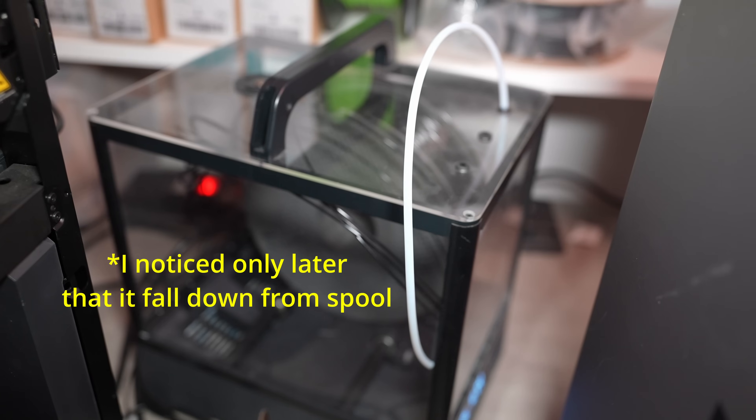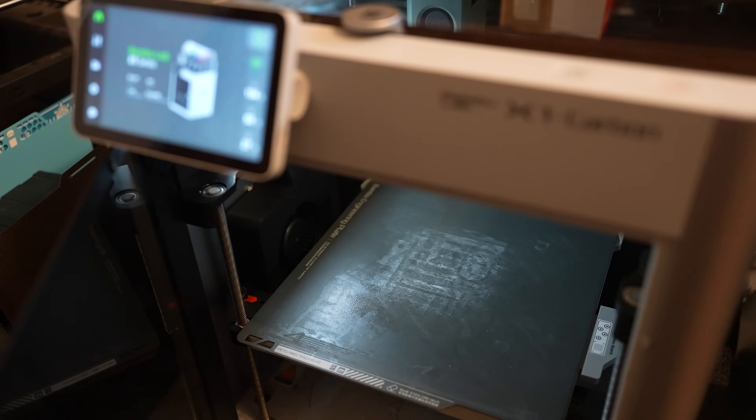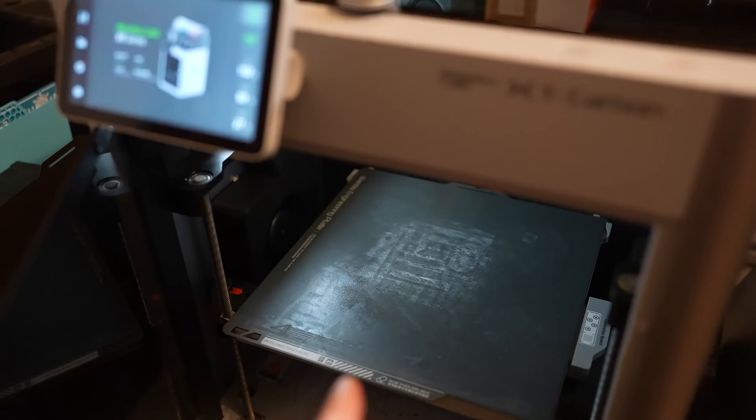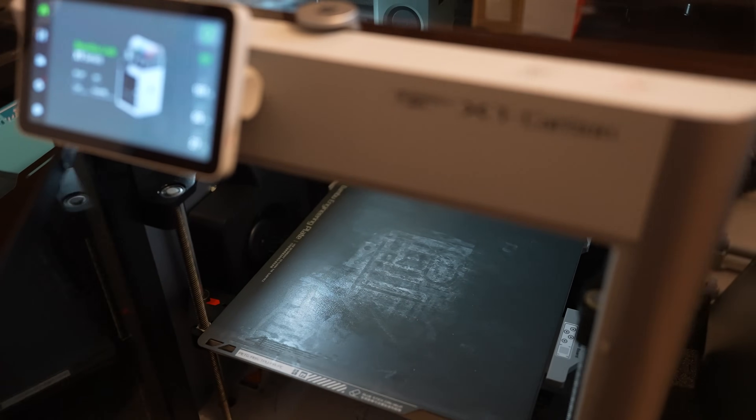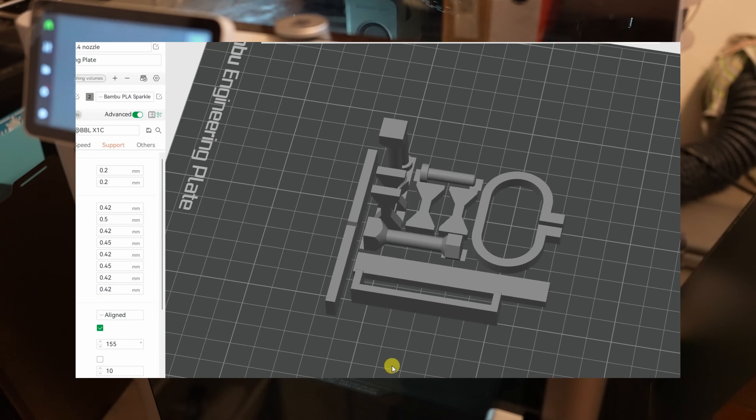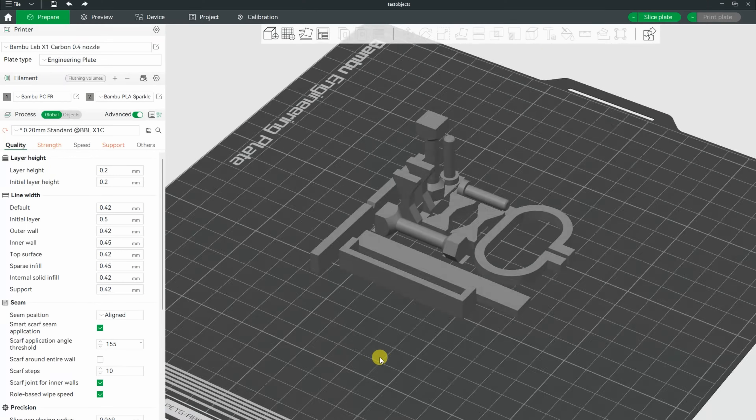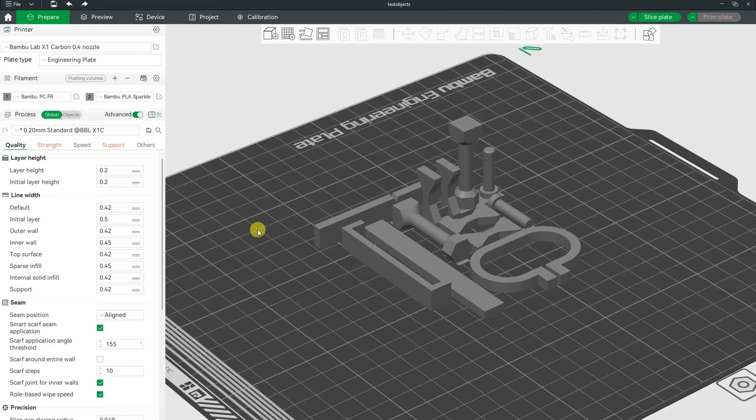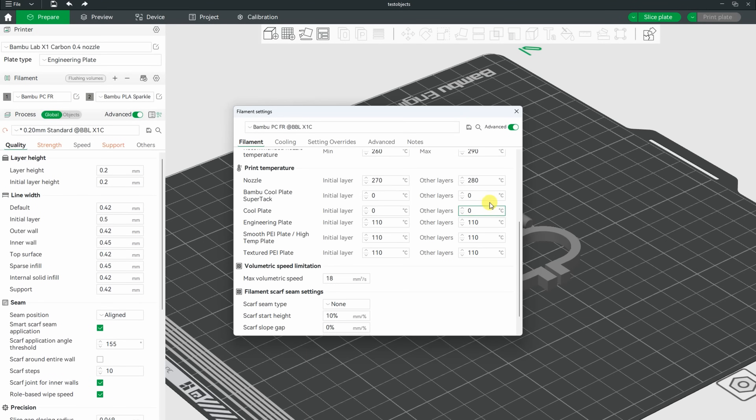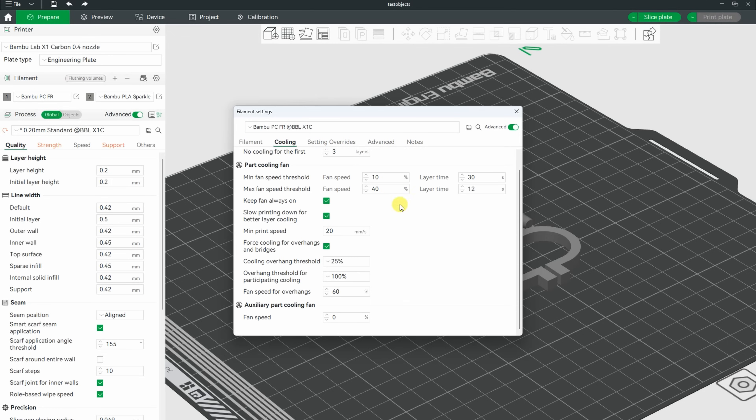I am starting with the drying, but it will be only 70 degrees Celsius for 4 hours. Printing will be on BambuLab X1, Bambu Engineering Plate with glue on it, and of course inside the enclosure. Let's see the settings in the slicer. We have the profile for this PCFR in BambuStudio: 280 on the nozzle, 18 cubic millimeters per second maximum flow. The default part cooling, different settings look OK, no sign of warping, and the printing is very fast.